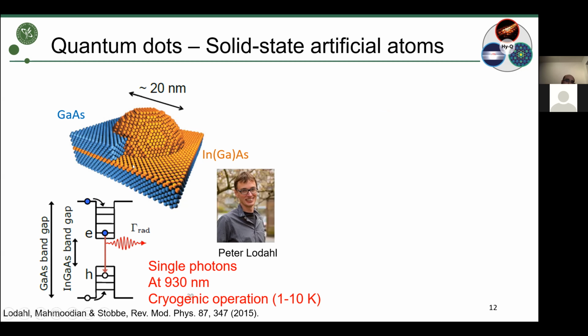And so what are they? They are basically little islands of indium arsenide, very tiny in size, surrounded by gallium arsenide. Indium arsenide is a low bandgap material, as you can see here, and it's surrounded by another material which has a much larger bandgap. So it basically forms a very tiny quantum well, with confinement in all 3 dimensions. So it's not just a simple quantum well, which would be just a 1D confinement, but a 3-dimensional quantum well, so a quantum dot.